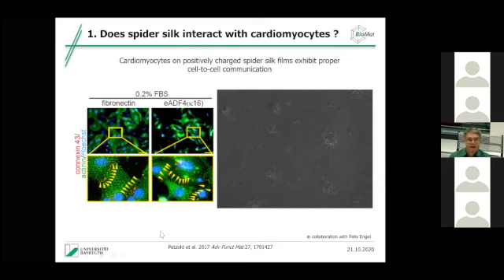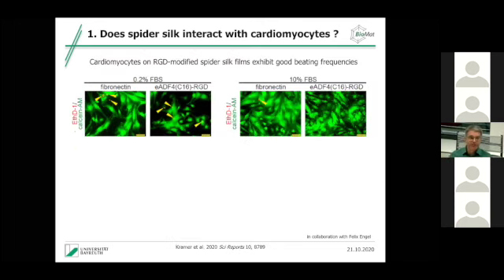So as soon as they start beating, they're very happy, they like it. However, this is 2D, yeah? But this was the very first important step, to find the right material. The question is, can we also use other silk engineering? And as mentioned at the very beginning, we can also introduce cell binding motifs like the RGD. So we tested again now, so this is our workhorse, the negatively charged protein, eADF4(C16), you know what that means. C is glutamic acid, so they have a lot of negatively charged groups. And now we added the sequence RGD. And you see now all of a sudden, well, this surface is also good for cardiomyocyte adhesion. And even if we increase the concentration of the fetal bovine serum, you see much nicer proliferation.